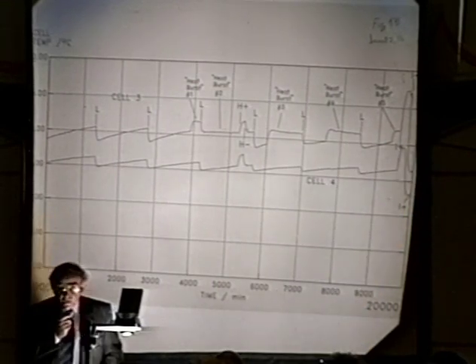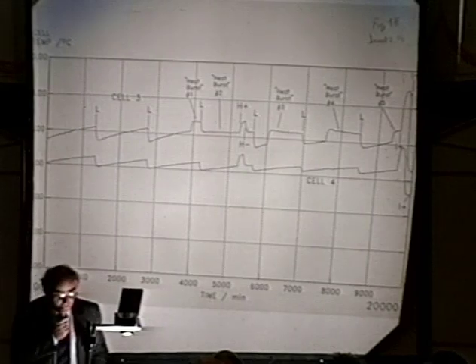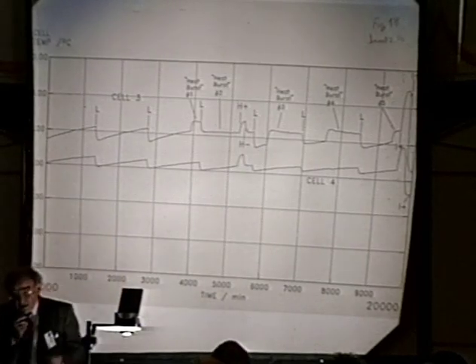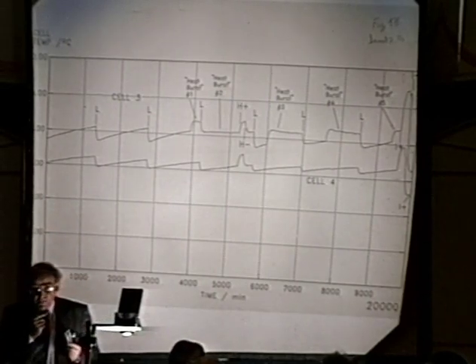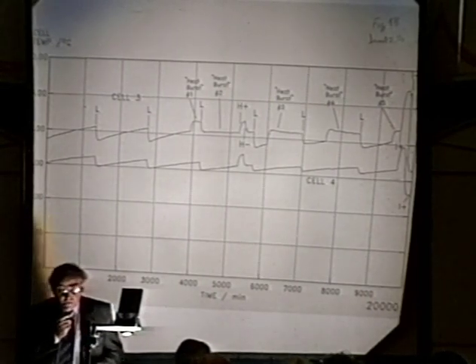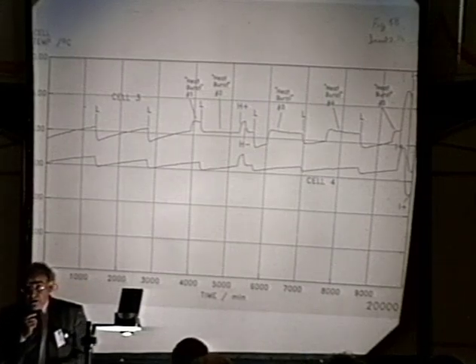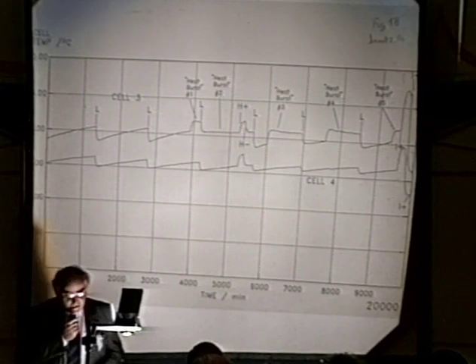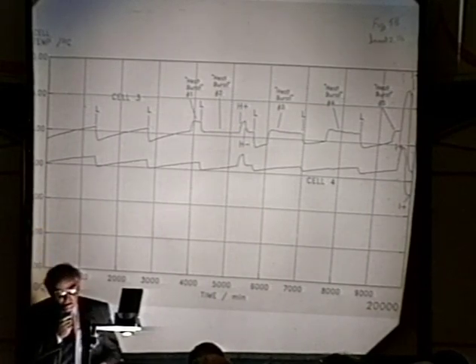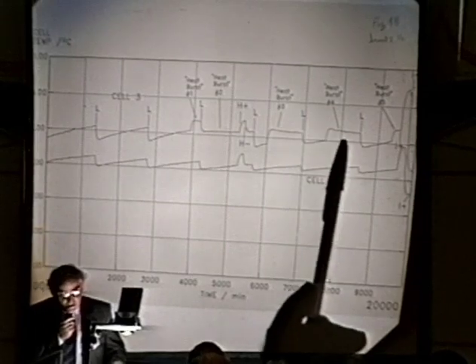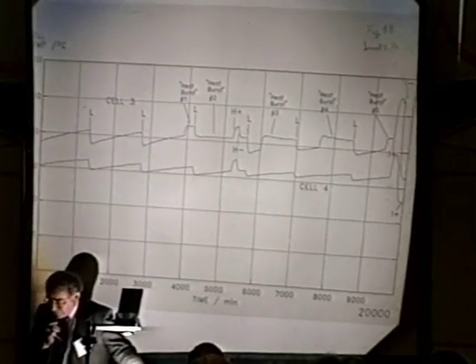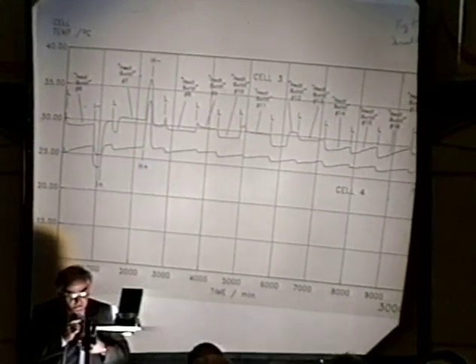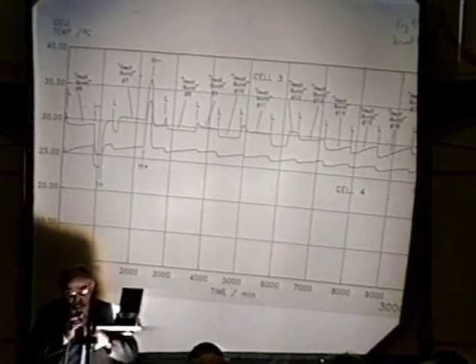Now, thermodynamic systems don't show excursions in temperature unless there's a source of heat. Either the experimental device is not sound, or else we must say that there's a source of heat. Now, I think Wolf Hansen's done a splendid job on it, and he tells us that this thing is correct to around 1% or so, so these excursions in heat really must be significant. Well, let's carry on with that. There are lots of these excursions, just for this particular cell. They're scattered about, I don't know, 27, 30 excursions in temperature.